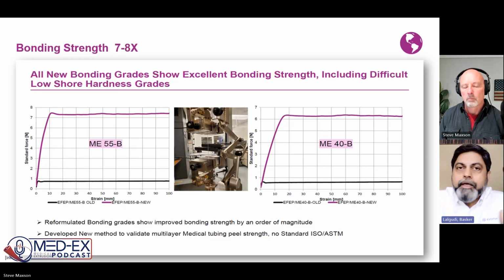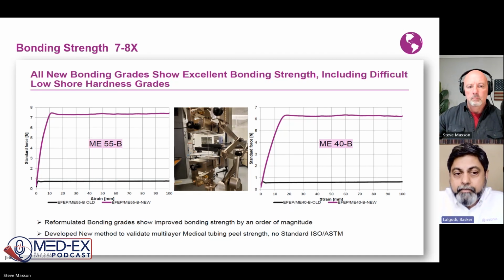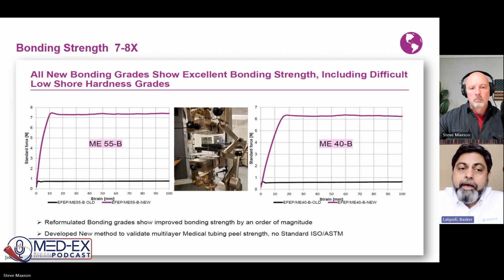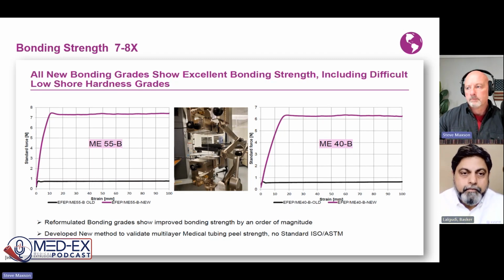There are no expensive adhesives. There is no treatment applied. It's one-step co-extrusion, bondable Vestamid Care on top of fluoropolymers like EFEP, Daikin RP5101, and that's the result you see. These are actual test data for 40B and 55B, and you would see something similar for ME62B and ME71B.